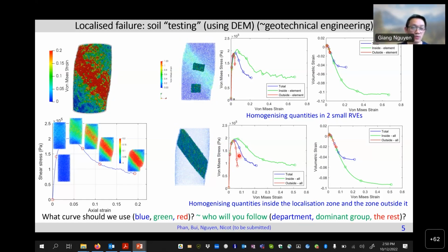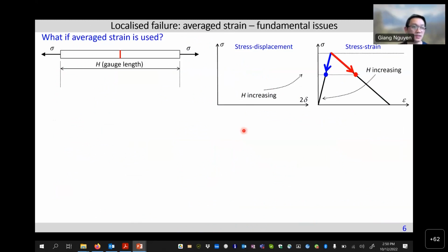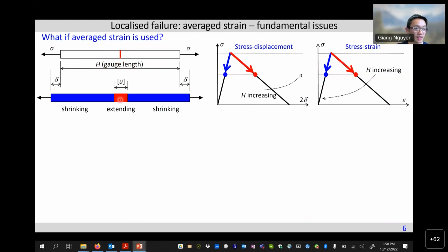Okay, so I give a 1D example first to have more fundamentals inside. So if we tension the bar like that, it cracks there. We put H as the gauge length, because in the end we need to work out strain from displacement. Okay, we tension it, it cracks in the middle. Because of the equilibrium, when the stress or force starts to reduce, it's 1D equilibrium. The stress or force outside and inside the band, the red zone here, should be the same. So if the zone here is extending, leading to fracture, the zone outside it should be shrinking, because it's not fracturing. It's still elastic. Elastic should follow the elastic unloading path.